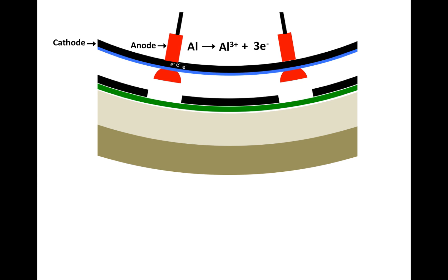The problem is, if those electrons just accumulate in the cathode, then an electric charge, a negative one, will quickly form, and no more electrons will be accepted from the aluminum, and the reaction would stop.